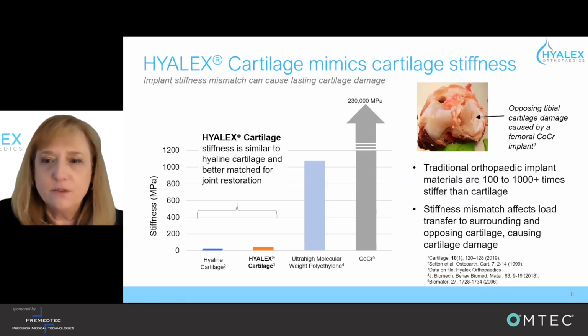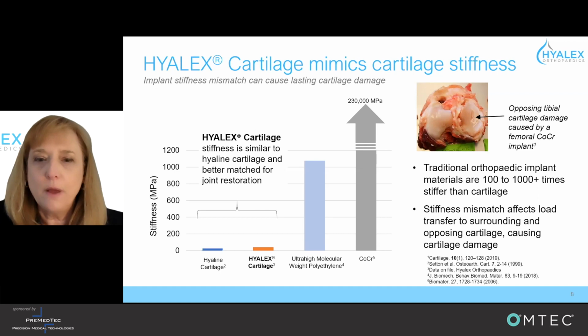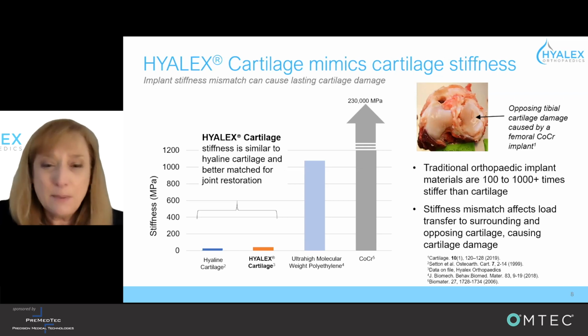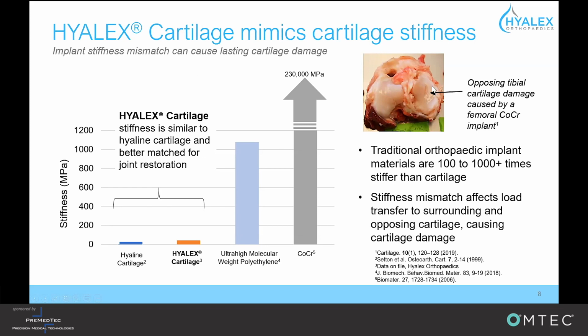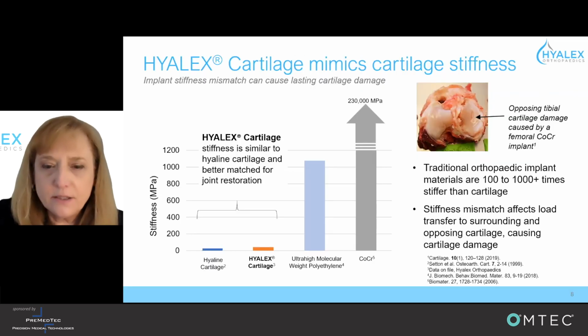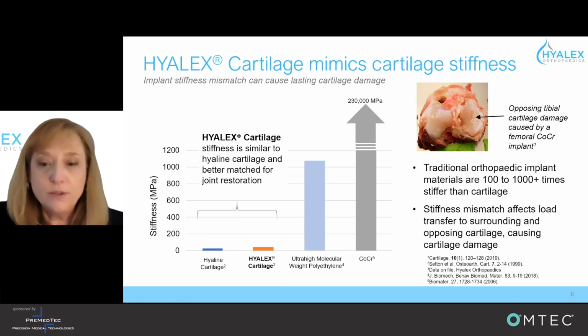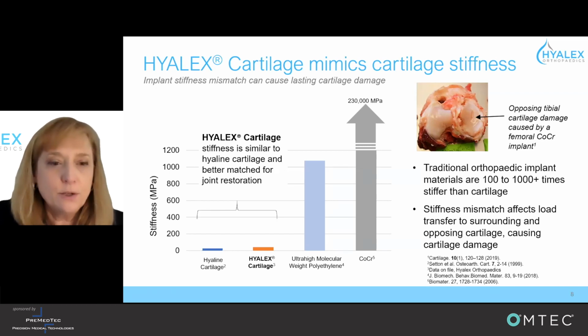When we consider the compressive stiffness, we know that traditional orthopedic materials such as ultra-high molecular weight polyethylene and cobalt chrome that are used for hip and knee arthroplasty implants are hundreds and even thousands of times stiffer than healthy cartilage. And despite this difference in the stiffness, these materials have been tried as cartilage repair implants. And then as the inset photo shows, the mismatch in the properties can result in long-term irreparable damage to the opposing cartilage surface. In contrast, the compressive stiffness of HYALEX cartilage is very similar to native cartilage. This allows loads to be transferred to the surrounding and opposing cartilage in a more physiologic manner, helping to preserve the joint tissues.